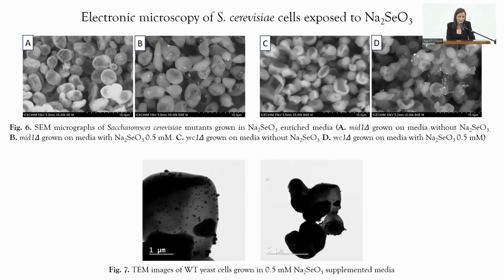The wild-type yeast cells were assessed through transmission electron microscopy. We confirmed once again the presence of selenium nanoparticles on the surface of the cell. But here it would be recommended that we optimize this method with a fresh biological sample next time for a more precise localization of the nanoparticles.